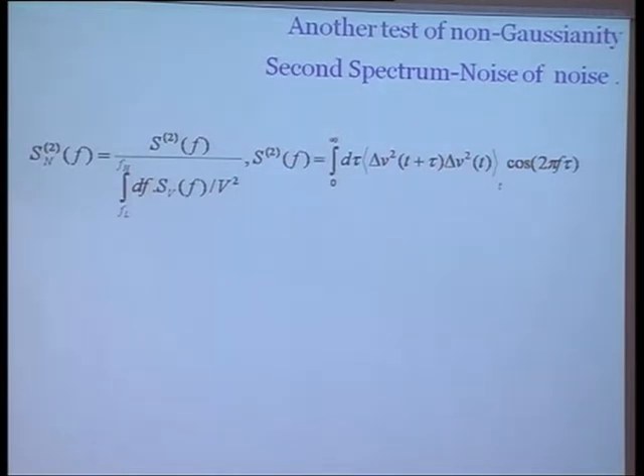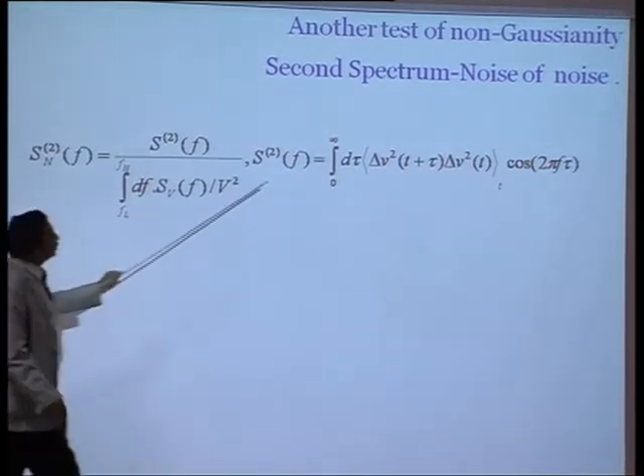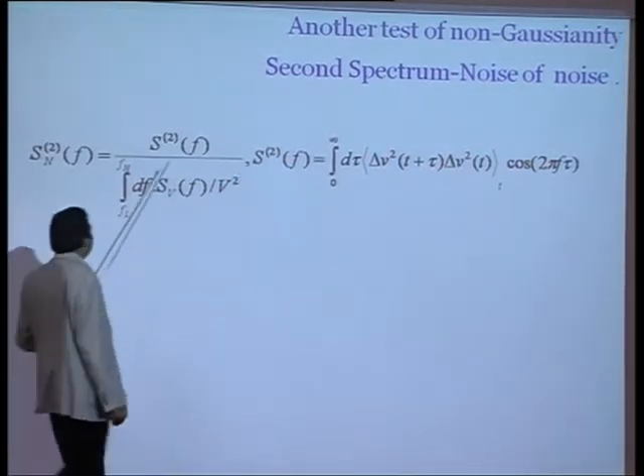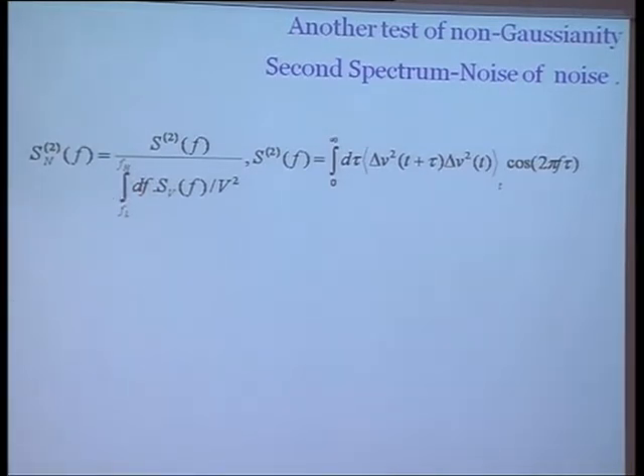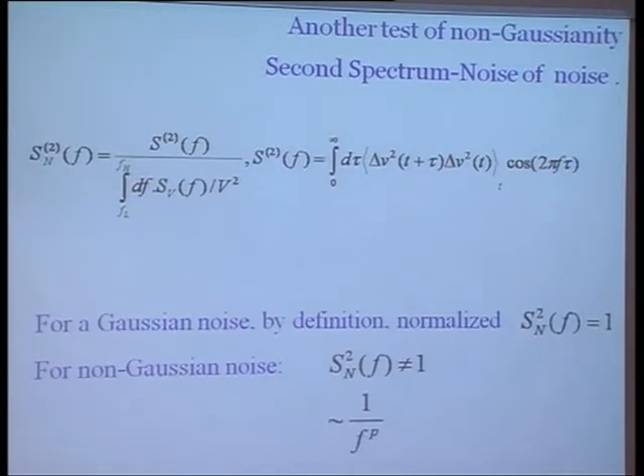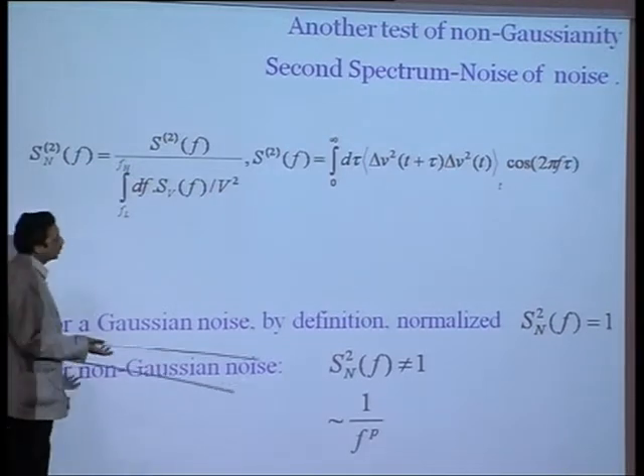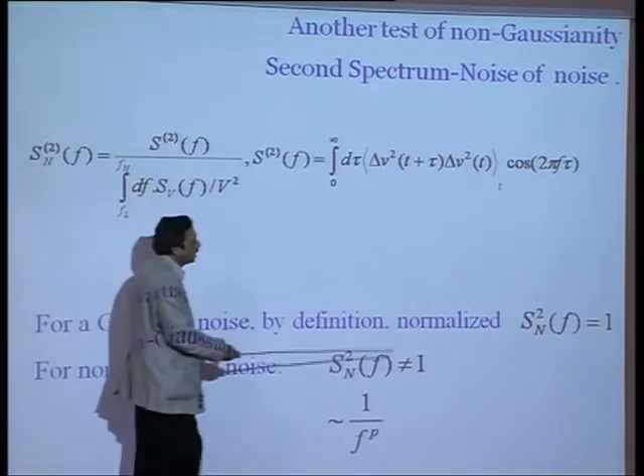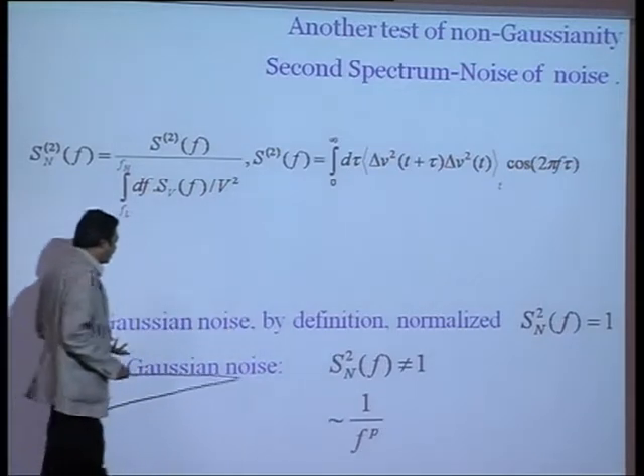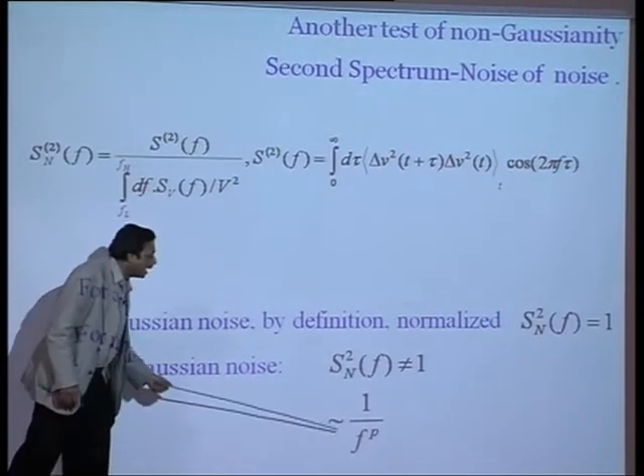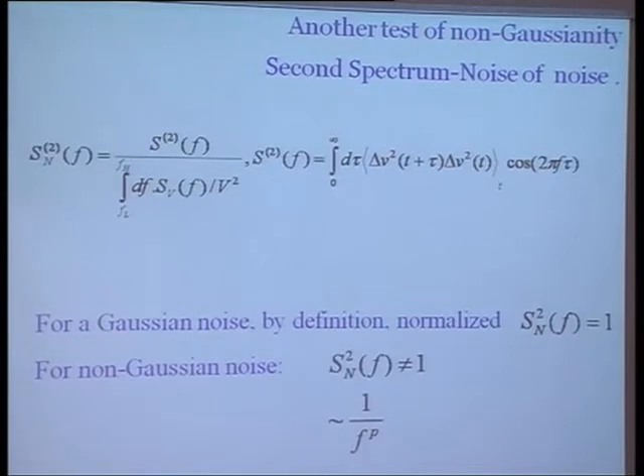And the second spectrum is nothing but you actually calculate the square of the power spectrum and you normalize it by the power spectrum squared. What you find there is that if it's totally Gaussian noise, then the second spectrum is determined by the first spectrum. So if it's a normalized second spectrum, it should be 1. And if it's non-Gaussian noise, then it is not 1, and you can get a time and frequency dependence coming into it.